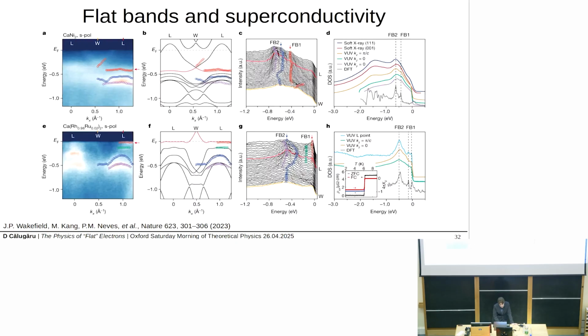So here in panel A, I'm showing the result of ARPES, that's angle resolved photoemission spectroscopy, right? And this essentially probes the band structure of an actual crystal, right? And you can see here that they've identified these flattish bands, right? And they've even compared them to theory. Now, if you have these flat bands quite far from the Fermi energy, then nothing really happens. But if you take the compound, you dope it. Doping means that you add different atoms with different number of electrons. You see that exactly when the flat band touches the Fermi energy, you actually get superconductivity developing, just like we did in twisted bilayer graphene.